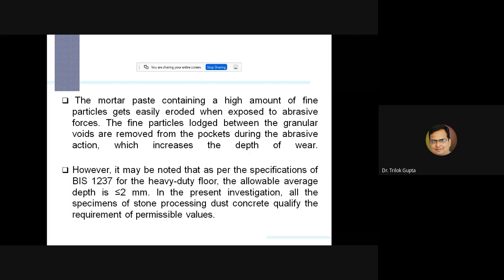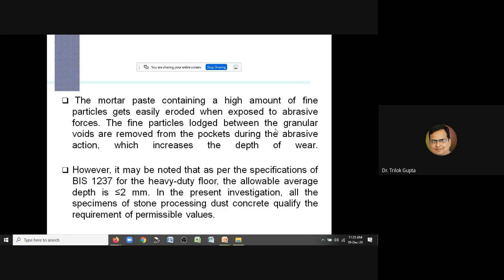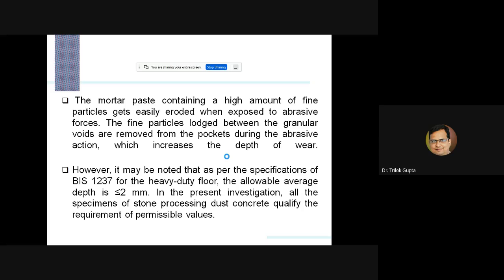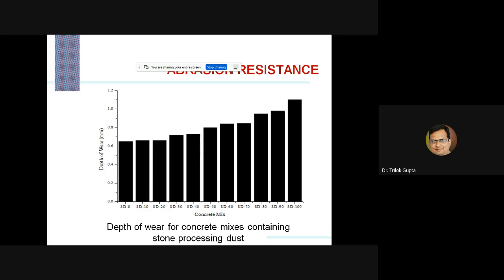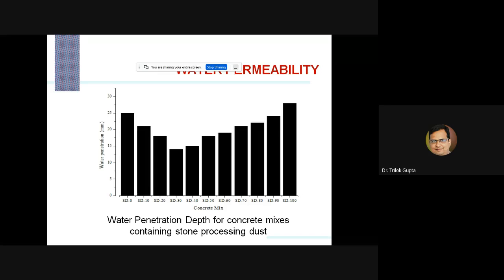And as per IS 1237, heavy duty floors allow an average depth of wear of less than or equal to 2 mm, and in our case the value was less than approximately 1.1 mm, even up to the replacement level of 100%. So we can use such type of concrete for heavy duty floors up to 100% replacement.